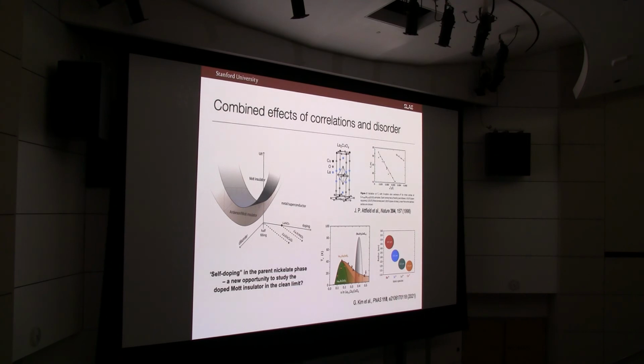And so again, a speculative viewgraph, but what's exciting us is that if that self-doping picture is correct, if I think about some sort of cartoon landscape of a correlation strength, a doping, and disorder scale, the slice we're taking with the nickelates is a little bit different from the cuprates. Namely, we're off of half filling by the self-doping, and we're taking certain trajectories in this space. And I want to compare that with what we might think we're doing in the cuprates, the 214 cuprates.